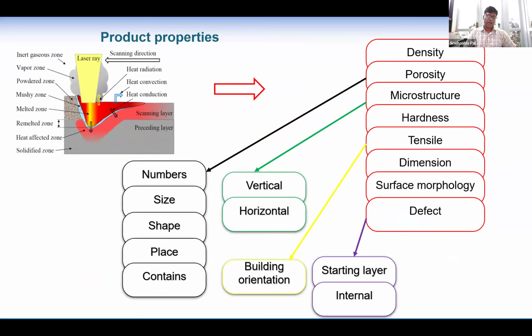We can control the melt pool characteristics, and accordingly we can get different results: density, porosity, microstructure, hardness, tensile, and other properties. There are many types of porosity we can get. It can be interconnected, it can contain particles or not, and the size and number can differ. Also the microstructure will be different vertically and horizontally, so tensile properties will also differ depending upon the building orientation. Defects in the starting or bottom layer will be different from the internal layers. So let's discuss density.